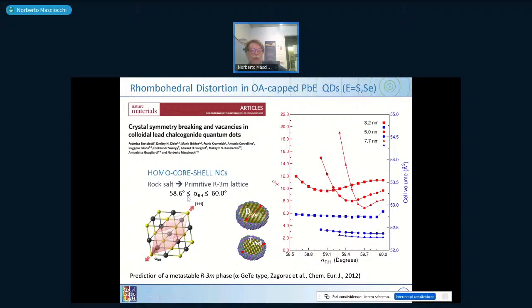So we have done simulations by changing the length of the vector, which means changing the angle between the three rhombohedral vectors from 60 degrees, which is the ideal one for a cubic system, to 58.6. Then we used, of course, the size of the core and thickness of the shell. So we defined a model which is in line with the most modern interpretation of these materials. And if you look at the blue curve, they are the cell volumes for different size materials, the 3.2, 5.0, 7.7 sizes. You see that the cell volumes are different. It means that lead sulfide has an edge length or a cell volume or a molar volume which is different depending on the size.